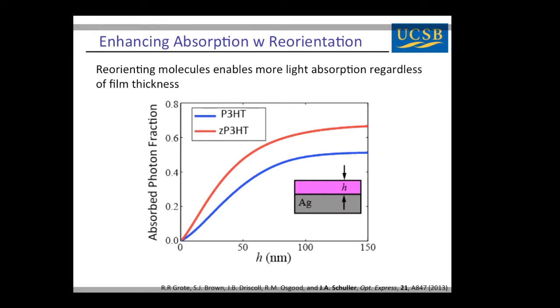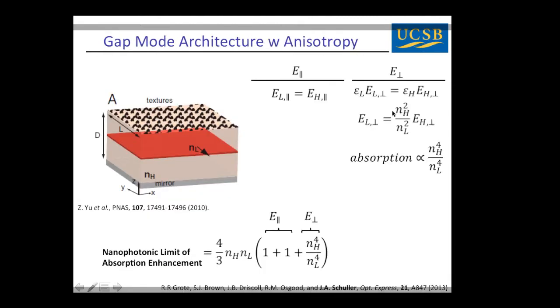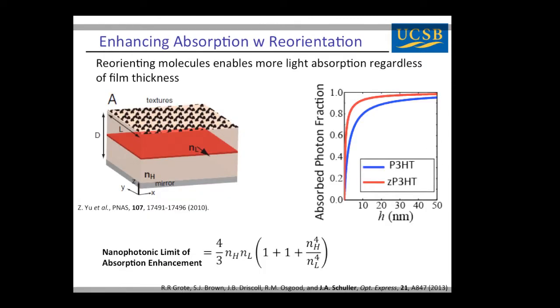But what we see here is that as a function of the thickness of the film, when you include a light trapping architecture, something that takes your incident light and scatters it into all the available modes of the system, it turns out the vertically oriented polymer in red has better absorption for all thicknesses. Okay? And when we look at the dielectric mode, we see the same.